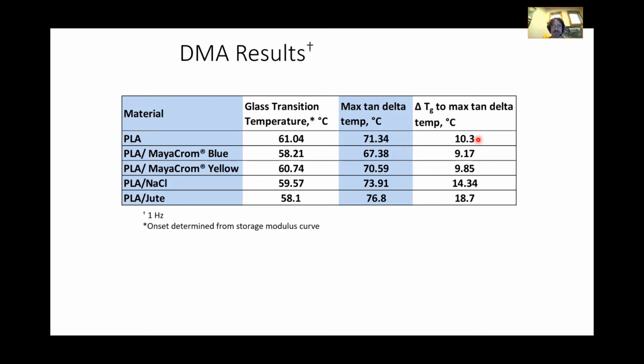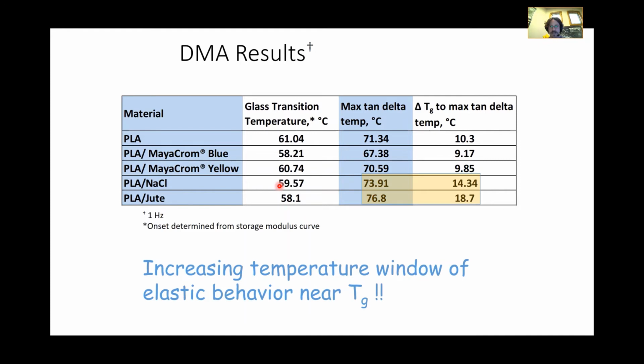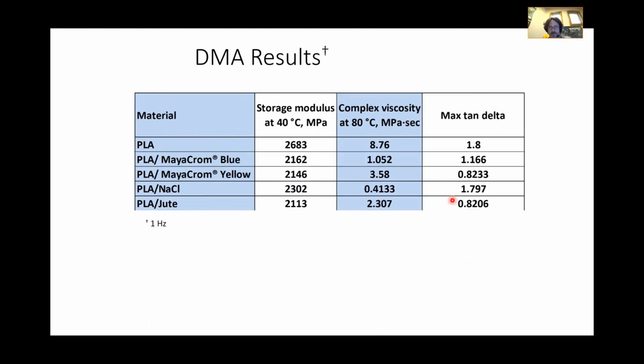So our DMA results, let me move the mouse out of the way. We have PLA, myochrome, and salt and jute, and there were slight effects on the glass transition temperature, but it had more profound effects on the window. It increased the window, so it allowed it to suppress melting, basically, is what I'm trying to say.